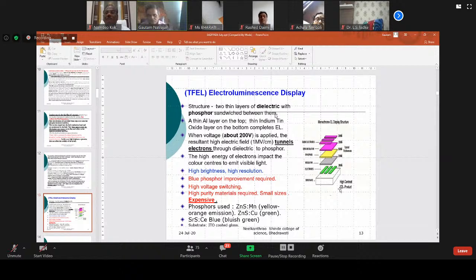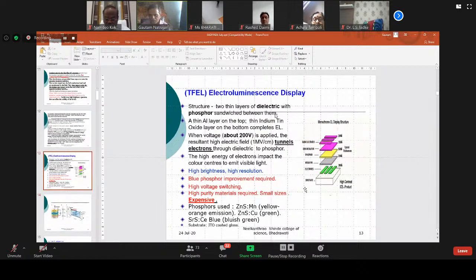Okay, we go to the next one. This is the structure. You can have a look. There is a substrate. Usually, the substrate is ITO coated glass. It can be plastic or wire also. And then you have electrodes. Electrodes are usually indium tin oxide for the anode, and aluminum here. Aluminum electrode on top, thin indium tin oxide on the bottom. And you can see insulator on both sides and in between the electroluminescent phosphor. So why the insulator? Otherwise electrical breakdown of the phosphor can occur, and damage can occur. So the insulator is like a protecting layer for the phosphor. So the electric field first goes to the insulator, then the electron is injected into the phosphor.